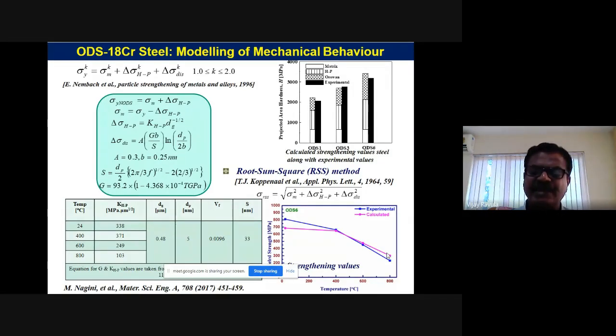But the problem is, as soon as you expose it to higher temperatures, there is grain growth, and as the grain grows, the strength comes down. But here, you are working on the material during the hot extrusion, so that's why you are getting a very fine grained structure, and also you'll have dispersoids on the grain boundary or within the grain, and these dispersoids pin the grain growth. So that is an advantage.